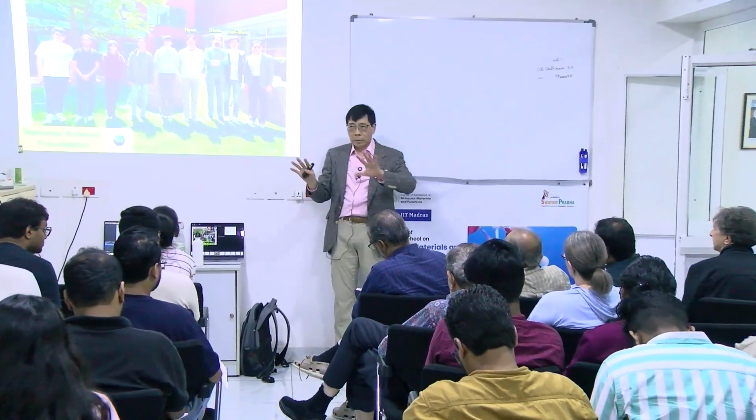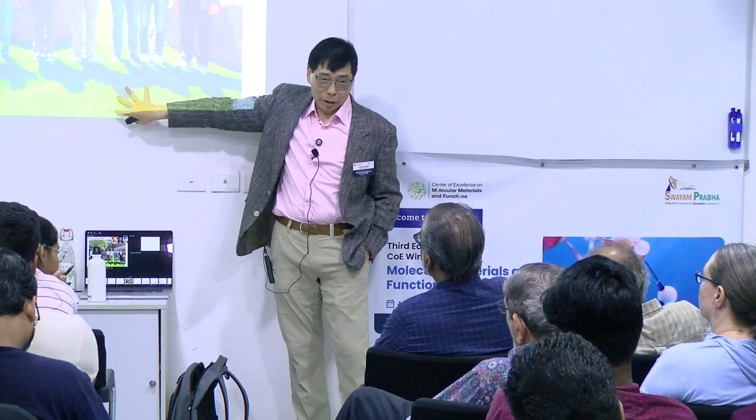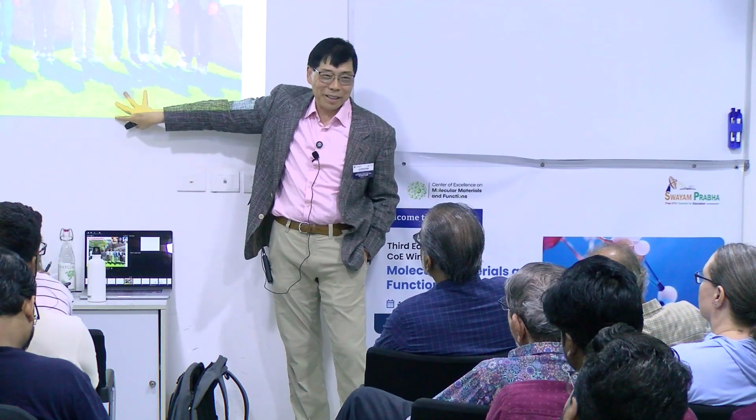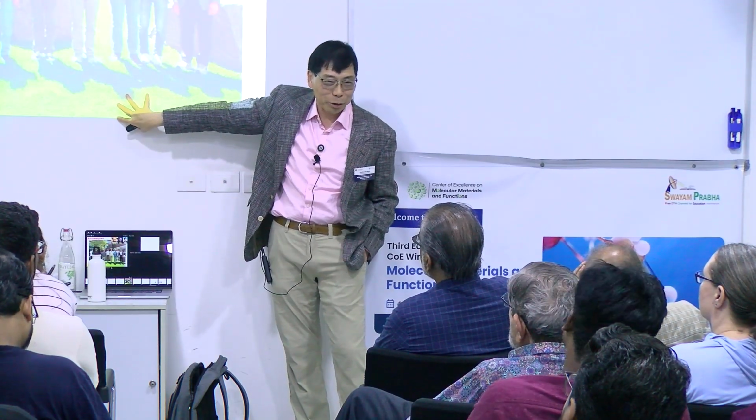So because you can have a different arrangement of the hexagonal vacancy, or you can have a different density, there are certain configurations that could be semiconducting. But the problem with this boron is, when you synthesize it, the challenge is how do you control what structure you make? Currently, I think that's still a challenge. I think the challenge is the same as a carbon nanotube. In fact, when you make a carbon nanotube, you actually make a mixture of many different diameters, different helicity. So boron, I think it's the same challenge.